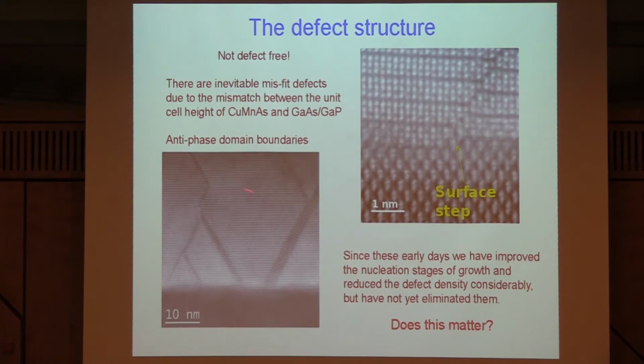And you can see in this very early sample, it was one of the very early ones that we had done, a cluster of these things. So they exist and they branch and they do things, and they might even contribute to the strain relaxation of the material. But since this rather messy early structure, we've certainly improved the nucleation quite a lot. The X-rays have improved, the full width half maxima have got less, and these things look a lot better, but I don't believe for one minute we've eliminated all the defects. We just haven't, okay? So does this matter? It depends. It depends what the defects do.